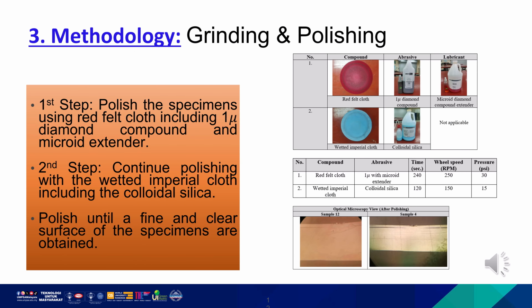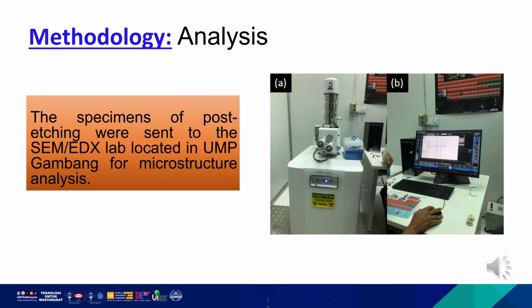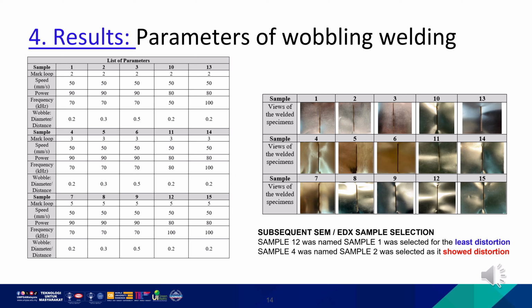The samples were, after laser welding, ground and polished subsequently with diamond compound and colloidal silica for a mirror surface finish. After that, the samples were sectioned and mounted, and the specimens post etching were sent to SEM EDX for microstructural and elemental analysis. So moving to the results, here are different parameters from 1 to 15 that were laser welded, and then we have the views of the welded specimen for all the samples.